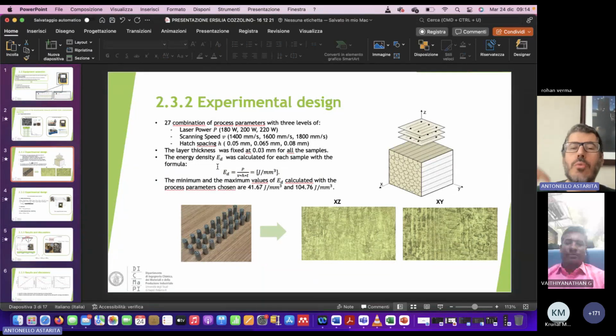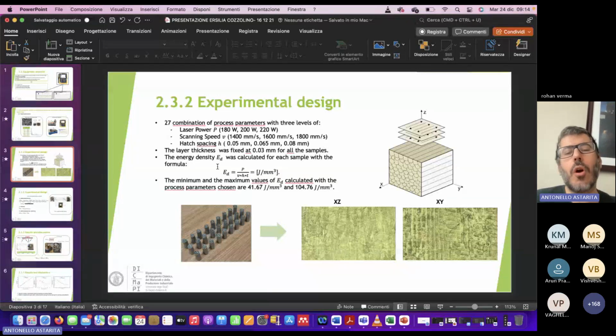But the effective amount of energy that the material is draining from the laser beam also depends on the shape of the powders, the packing factors, and the physical properties of the material itself. So another important point in trying to reduce the energy consumption is to increase the percentage of energy which is effectively drained by the powder bed material. So another important point is to choose the shape and the properties of the powders to increase the amount of energy which is effectively drained from the laser beam.